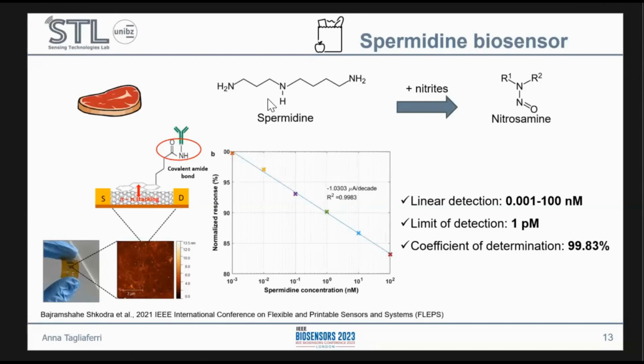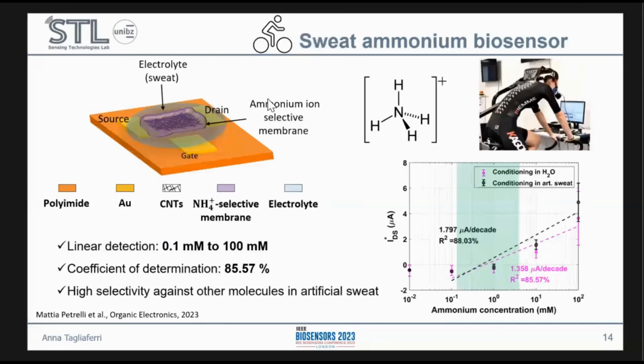You can see that for this example, we obtained a linear detection with a very high coefficient of determination, close to 100%, with a very wide linear range of detection from 0.001 to 100 nanomolar, and a limit of detection in the picomolar range. This was one of the cases where the carbon nanotubes were very unstable, and I will show you later what I mean by that. Further, the step that we took was to drop cast an ammonium ion selective membrane on the carbon nanotubes.